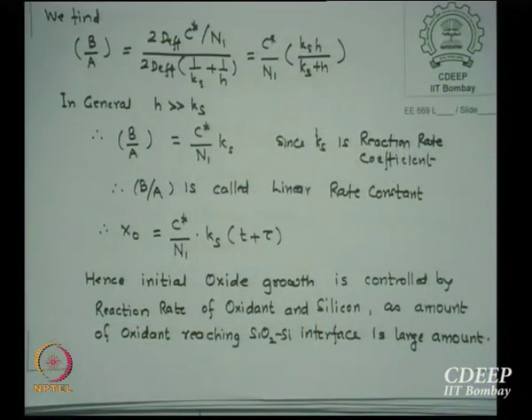So we then write this as x0 equals C star by N1 Ks times (t plus tau). So the initial oxide growth is related to time as linear growth. And it is also limited by the available reaction rate at the interface. Please remember, it is the availability of silicon atoms which can react. I may have enough oxidant, but not all of it is able to react. Initially enough oxidant has come, but there are not enough bonds where the Si-O bond can be formed. So the growth rate is limited by available bonds. So it is essentially decided by Ks, which is temperature dependent, okay.